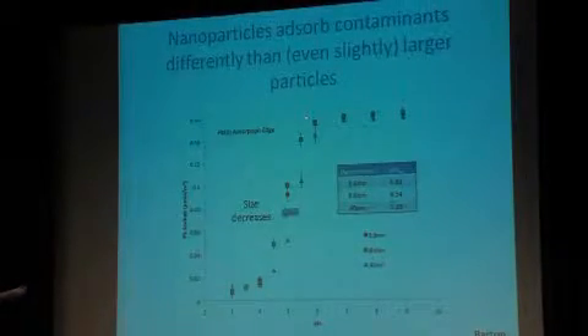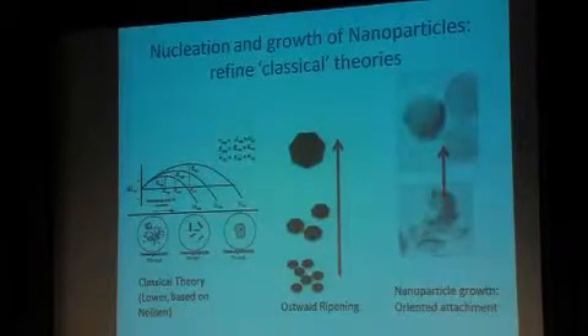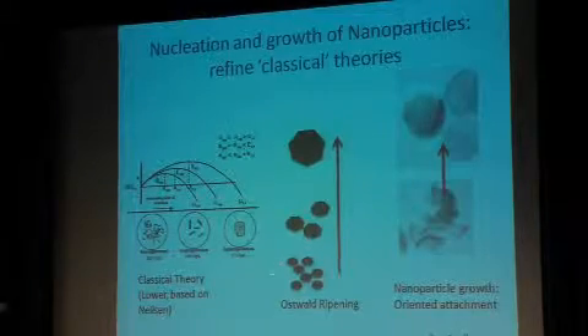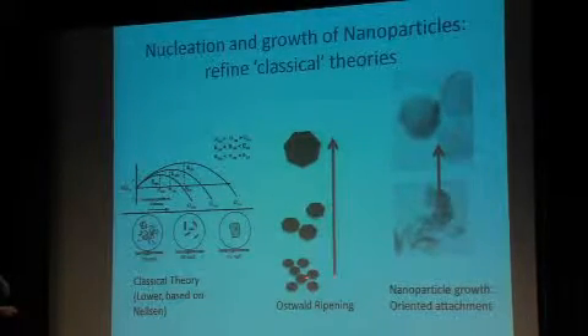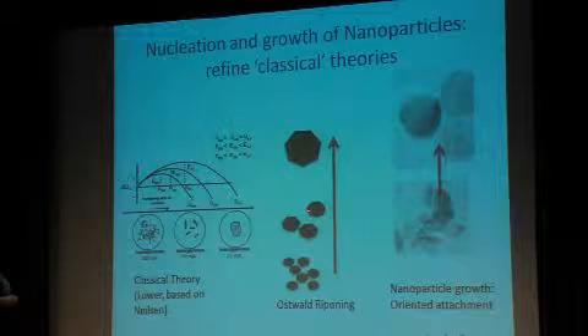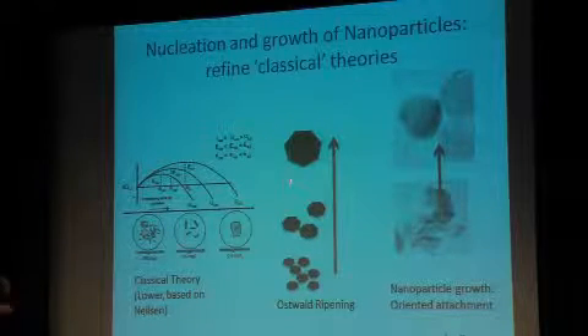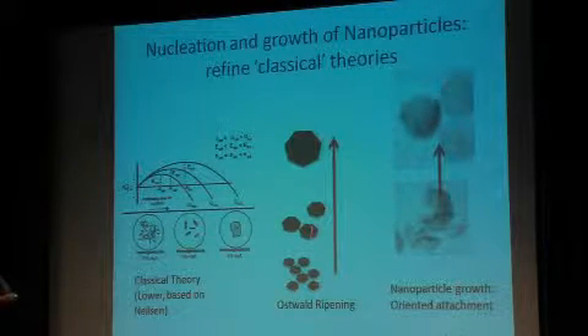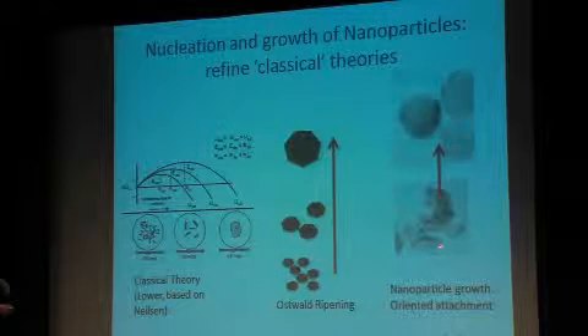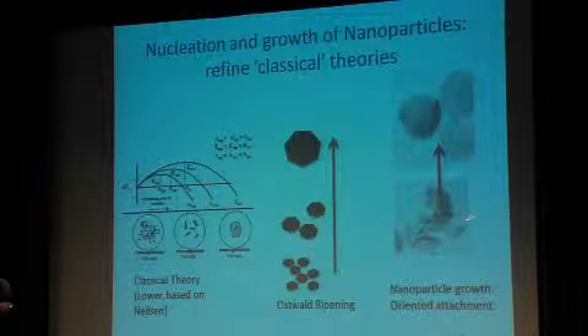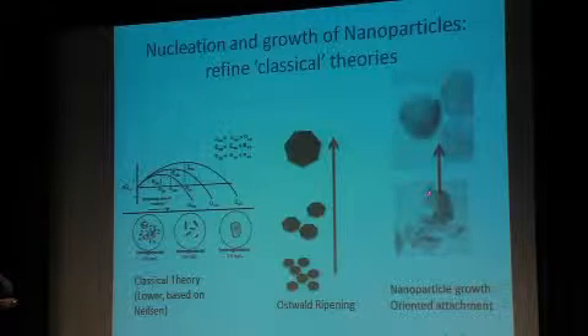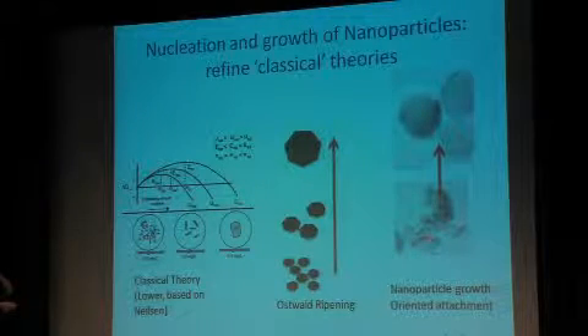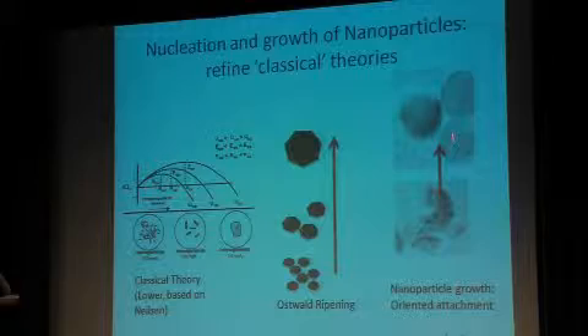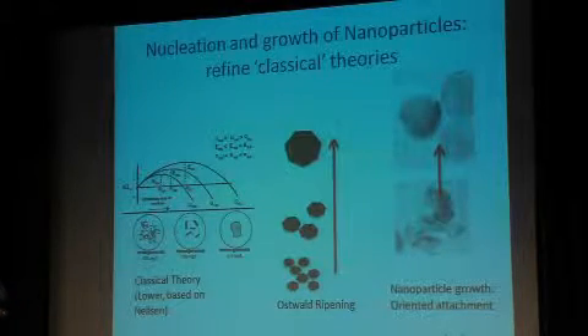Adsorption. Here we've got the same particles, how they adsorb lead as a function of pH. A little different for the nanoparticles versus the larger particles. It's often thought that very small particles are not very stable, and they will dissolve and ripen into larger particles over time. It ends up nanoparticles don't necessarily follow this. Instead, they grow by something called oriented attachment, where here little rhombohedral particles are self-organizing into hexagons. And so you're able to go from a very small particle to a larger particle by an entirely different route.